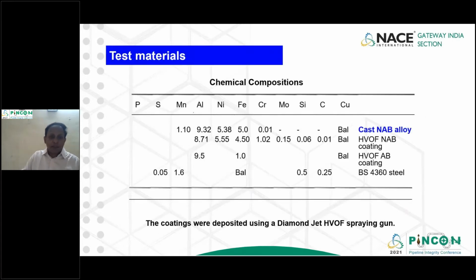This is the actual composition of the cast NAB. If you look here, the major component is copper. Though its name is bronze, nickel aluminum bronze doesn't have any tin content. It contains major components like nickel, aluminum, and iron. Aluminum comes to 9 to 10%, nickel and iron around 5 to 6%, and the rest of the elements are like chromium, with balance copper.